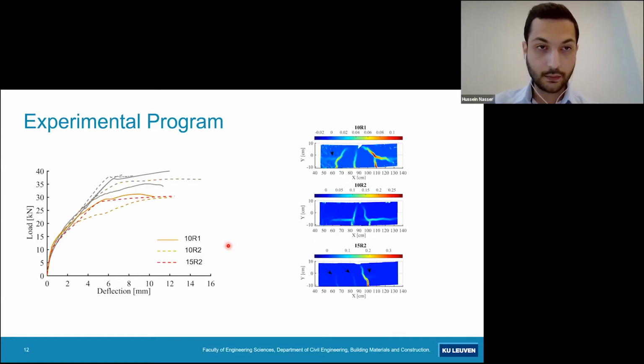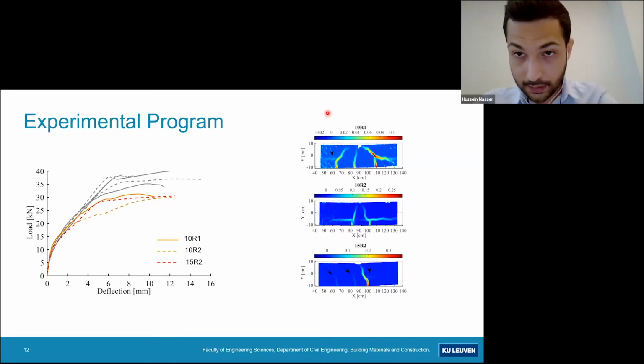it also changes the failure mode from yielding to formation of a splitting crack or debonding crack. If I also move to higher corrosion levels, namely the beams that reach 10% of corrosion, further reduction in the bending capacity and stiffness can be observed. If we look to the right at the strain maps obtained from DIC, a reduction in the cracking pattern is observed. Most beams showed 3 cracks, and the beam in the middle, 10R2, showed 2 cracks and a severe formation of splitting crack, indicating as well the effect of bond deterioration.